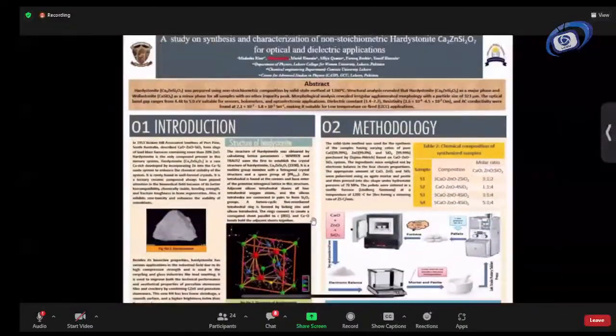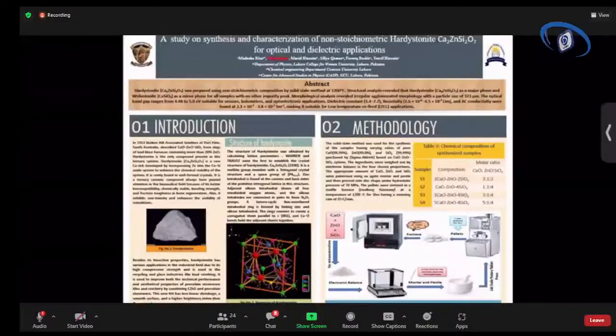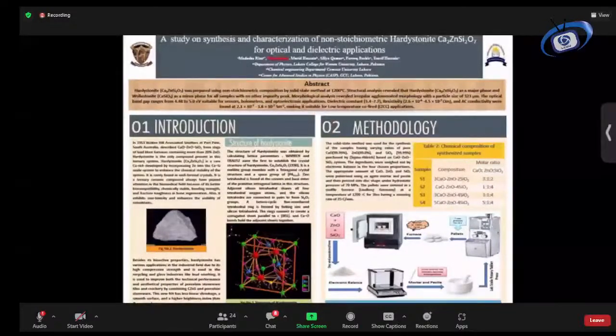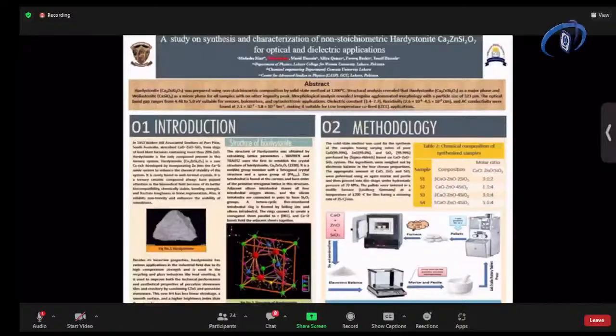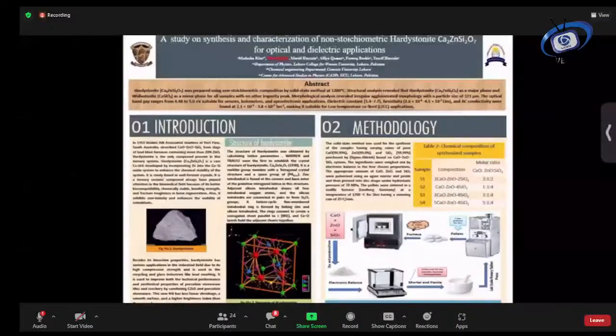Optical and dielectric applications. So the abstract of my poster is: Hardystonite was prepared using a non-stoichiometric composition by the solid-state method at 1200 degrees centigrade. Structural analysis revealed that Hardystonite is the major phase and Wollastonite is a minor phase with no other impurity. Morphological analysis revealed irregular morphology with particle size 323 micrometers. The optical band gap ranges from 4.48 to 5.0 electron volts, suitable for sensors, bolometers, and optoelectronic applications. Dielectric constant from 3.4 to 7.7, resistivity from 2.6 x 10^-8 to 4.5 x 10^-7. AC conductivity was found at 2.1 to 3.8 Siemens per meter, making it suitable for low temperature co-fired applications.